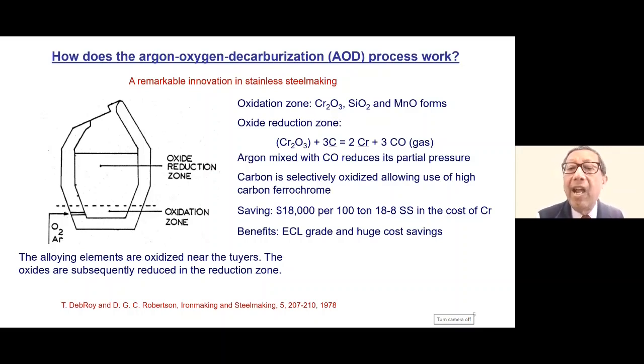Remember that high carbon ferrochrome can now be added because we can oxidize carbon without oxidizing chromium. And the difference in the price of chromium in the high carbon variety and low carbon variety of chromium is 50 cents a pound. A 100-ton heat containing 18% chromium will have 36,000 pounds of chromium.